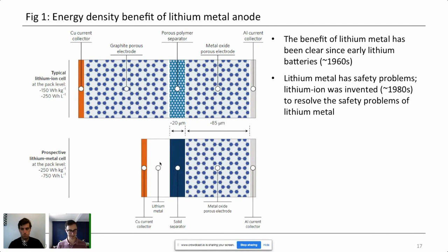It'll grow in these high surface area structures that A, are not very energy dense, but B, and more significantly, they'll actually grow through the holes in this porous polymer separator and grow from the anode to the cathode. And once you have a metal like lithium that bridges between the cathode and the anode, you have an internal short inside the battery. So electrons can then travel through that lithium inside the battery, from the cathode side to the anode side. And this internal short is responsible for most of the safety problems that you'll hear about in batteries. So when the Boeing Dreamliners were grounded a few years ago, or when the Samsung Note had to be recalled, that's because they had internal shorts inside the battery that caused safety problems.